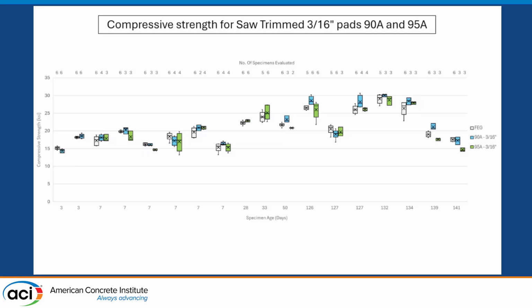And what I'd like to note here is that the box shows the interquartile range. So this is the inner 50% of the data points. And for the 90A 3/16ths and the 95A 3/16ths, it almost always overlapped with some of the data of the fixed and grinded condition. So this enhanced our theory that maybe this could be a good solution instead of fixed and grinded.